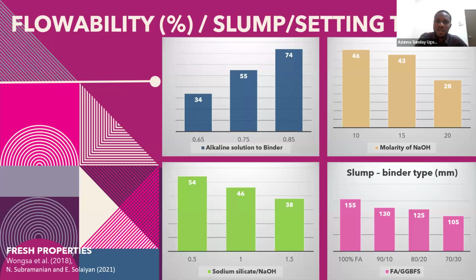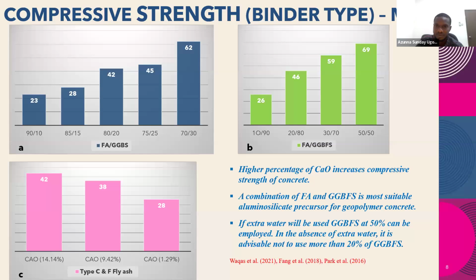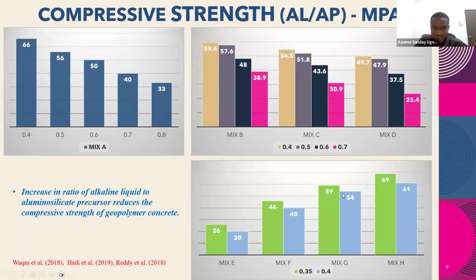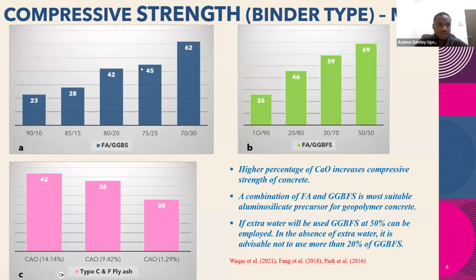So essentially that is what it means. If we are designing a concrete with high workability, we have to use a high alkaline to binder ratio. We have to use a molarity that is not very high. Also, the ratio of sodium silicate to sodium hydroxide has to be low. Then you have to use a binder with less calcium oxide in it. Then I'll now go to the compressive strength and the factors that affect compressive strength.